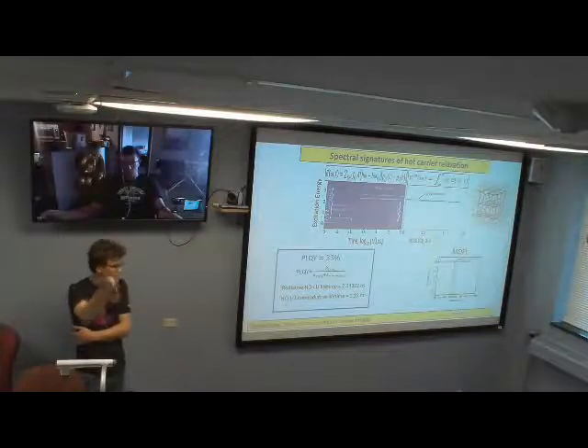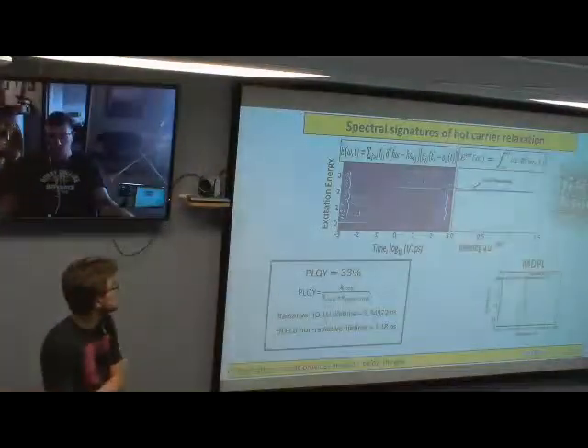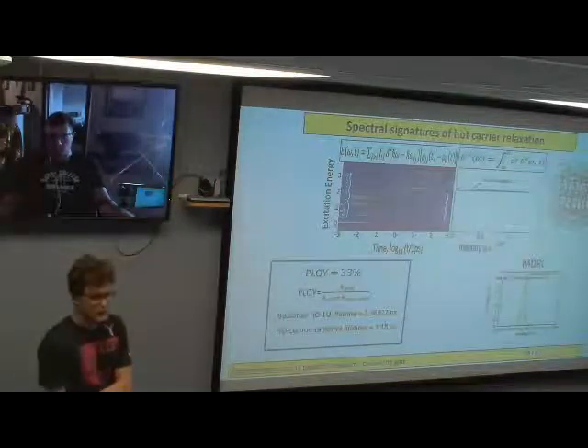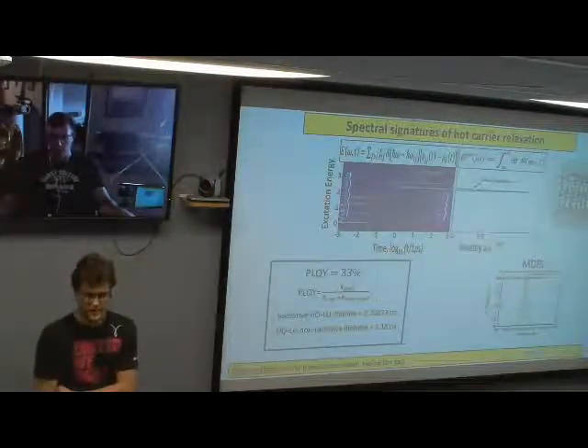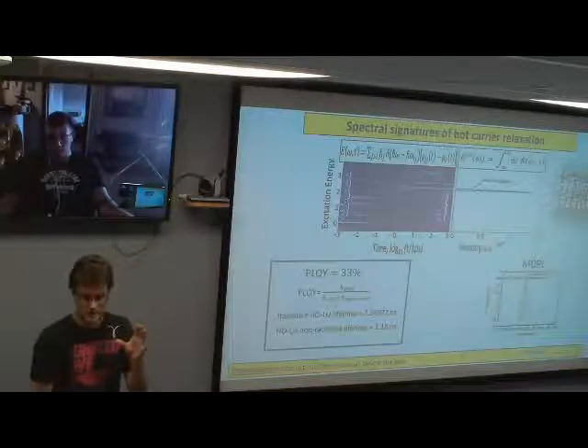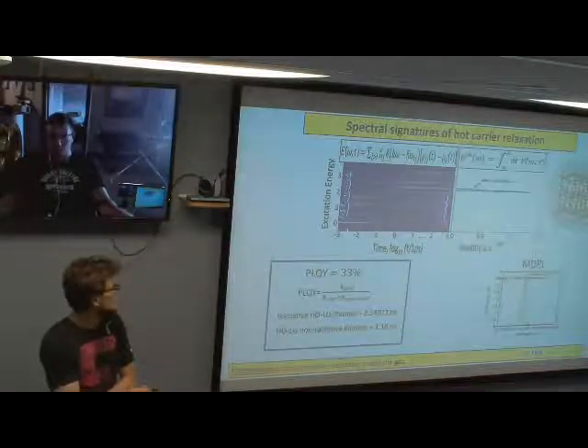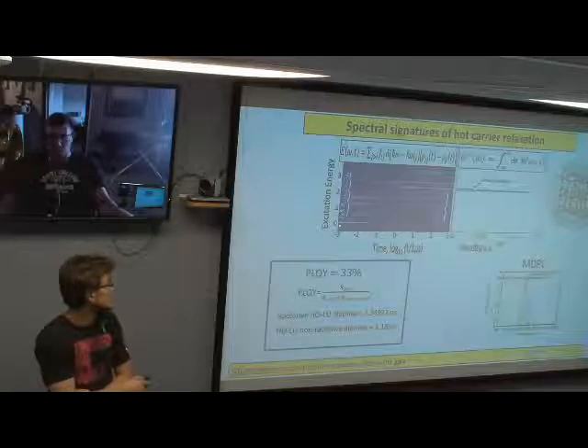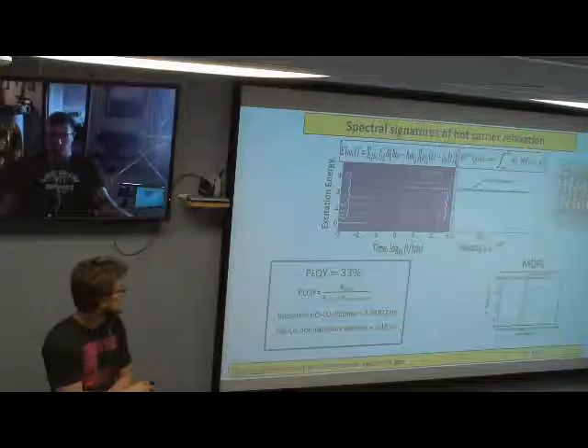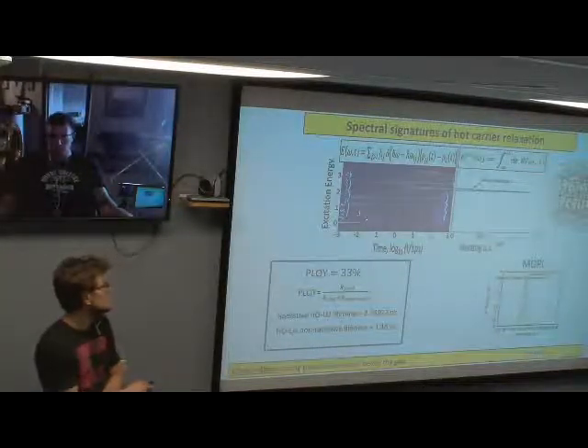And so along our excited state trajectory, we can compute the photoluminescence of this material if we just consider the oscillator strength of transitions while the electron and hole are at a certain occupied state and time. So this figure here would be a time resolved photoluminescence. You can see very early in the trajectory there's low energy heat dissipation that competes with non-radiative relaxation. So it's basically like IR heat that's given off. And then once it fully relaxes to the band edge, you see that it gives a very bright, intense PL.